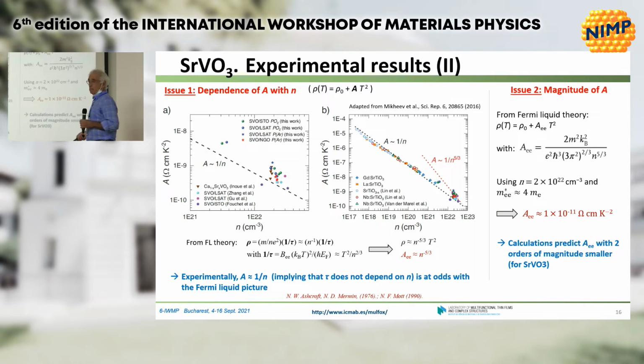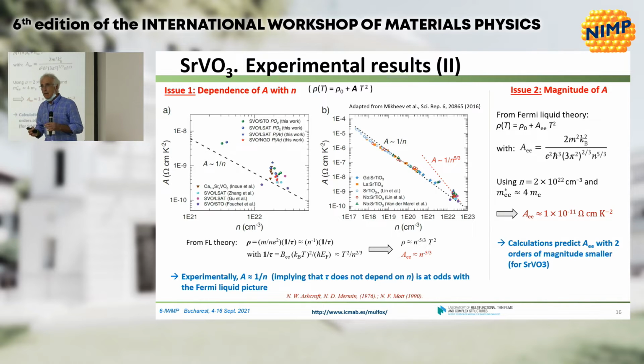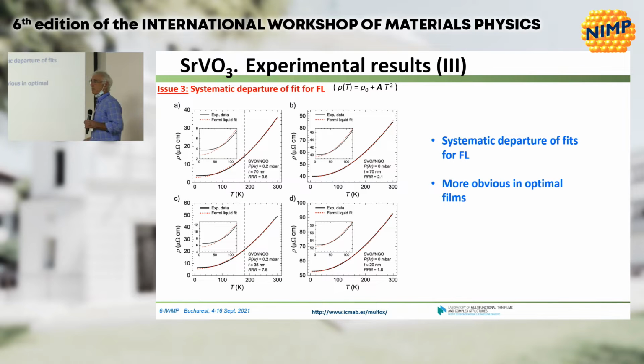There is also a numerical problem. The amplitude of this T squared term you can find in the books of Mott and Ashcroft or whatever. You're going to see that you can evaluate it in that way. So you do the evaluation. You know all the parameters, and you get an amplitude of 10 to the minus 11. And here, you are far from that. So there is a problem on the physical dependence on n. There is a problem on the magnitude of A. And there is another problem.